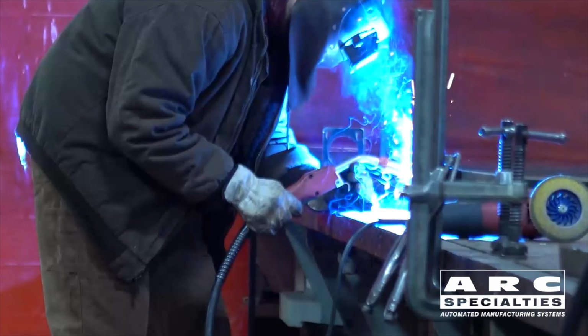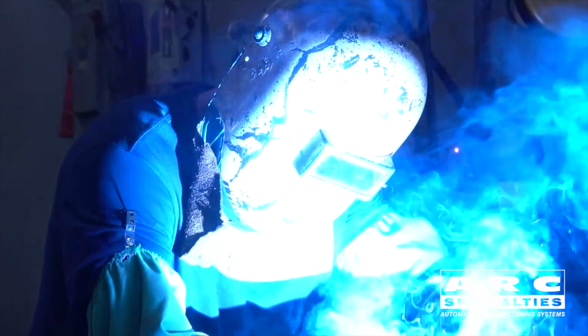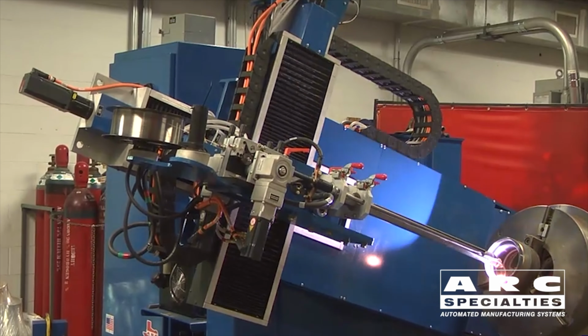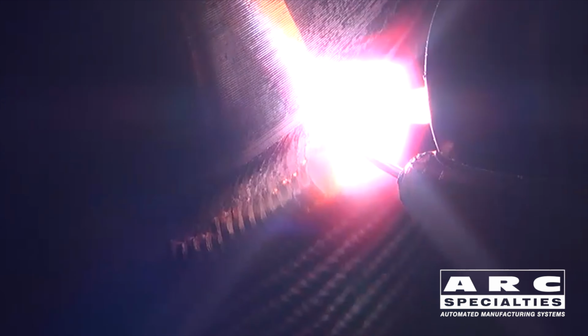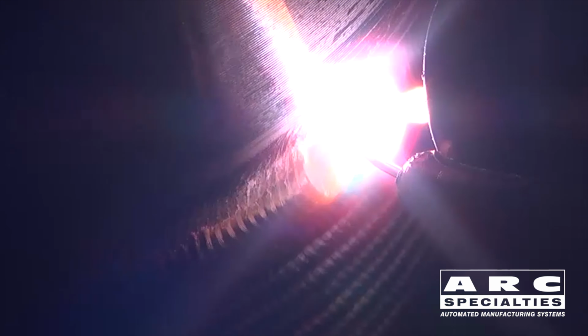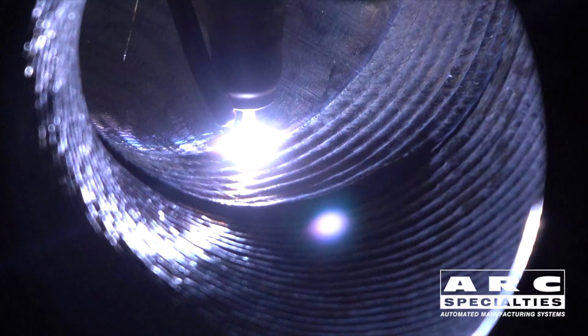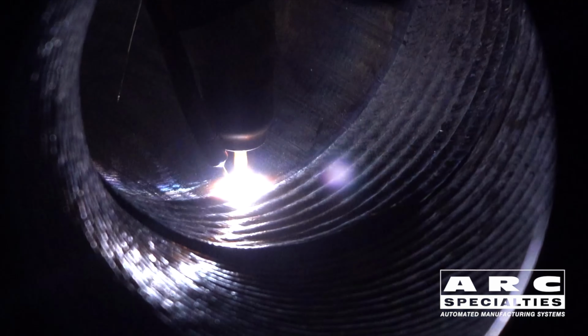In my world, hydrogen problems are primarily either welding or H2S sour gas. In welding, we avoid them using low hydrogen welding procedures. And to mitigate the problem of H2S or sour gas in petroleum, we use a gas tungsten arc Inconel overlay on all the wetted parts inside of valves and pipes to avoid stress corrosion cracking.